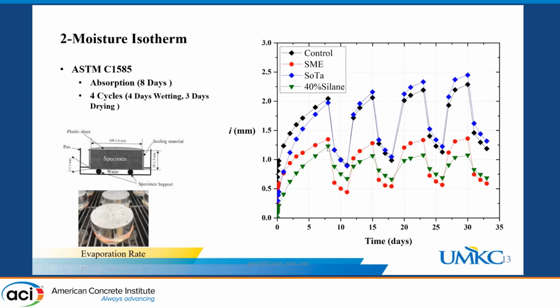Looking at the graph, we can see that all of the sealers reduced the absorption capacity, but to different degrees. Soy methyl ester and silane significantly reduced the absorption capacity over 8 days, while the sodium tartrate sealer was not as effective. After 8 days, we followed 4 cycles of 3 days drying and 4 days wetting to represent what's going on in real life.